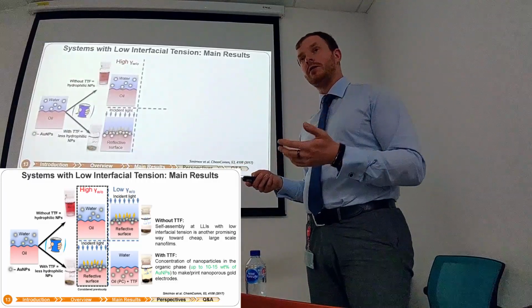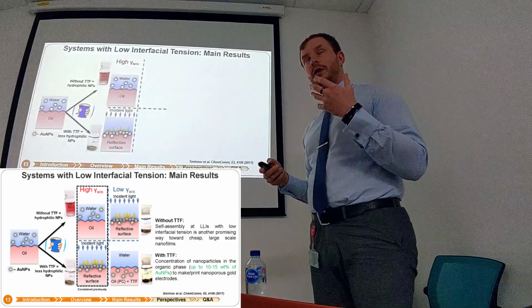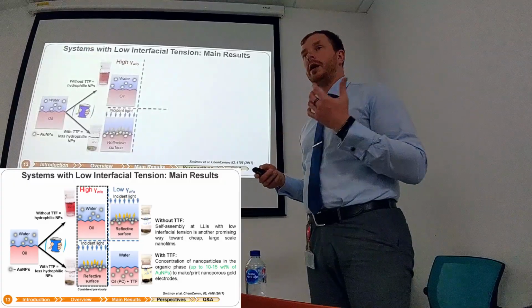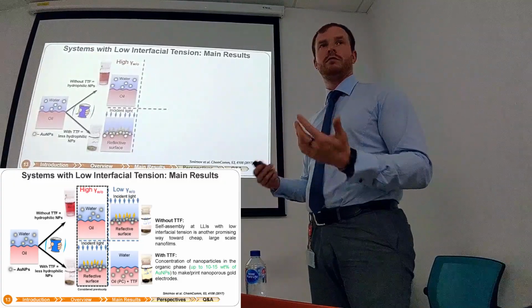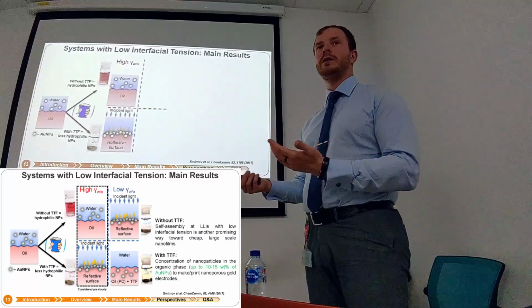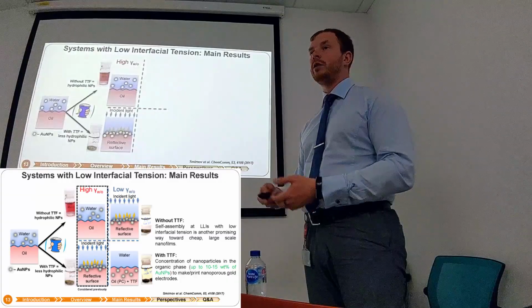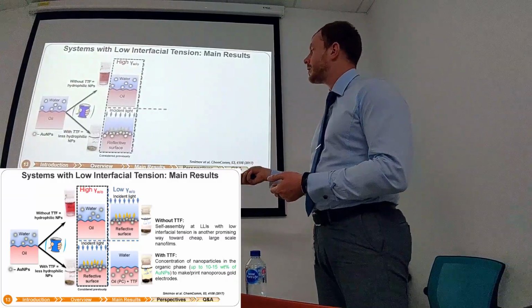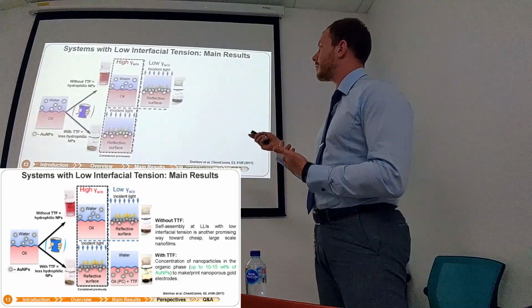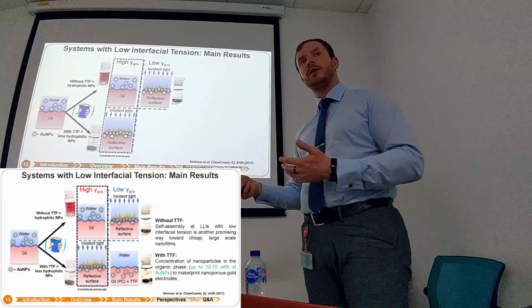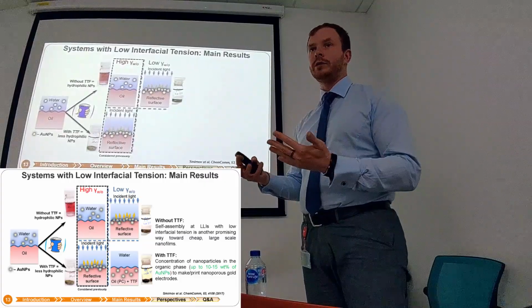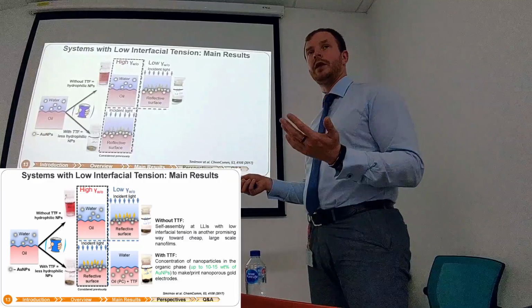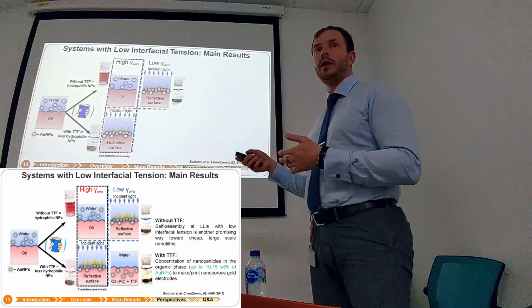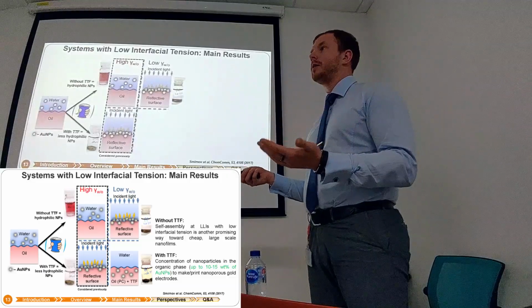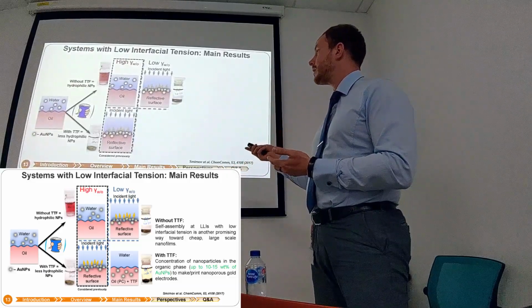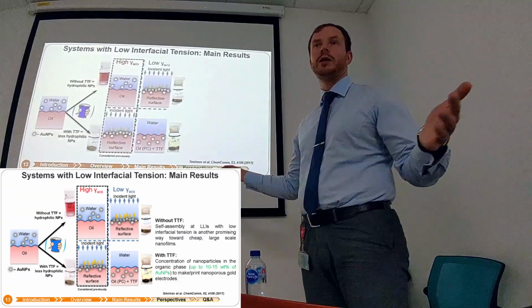There are many solvents. Some solvents have with water a very low surface tension, sometimes extremely low. As a researcher, sometimes you ask, okay, what happens if I choose a very low surface tension? Yes, we did that. We selected nitromethane and propylene carbonate, which are alike in that respect. And we observed that even without TTF we can assemble a quite reflective film on the surface of these solvents.